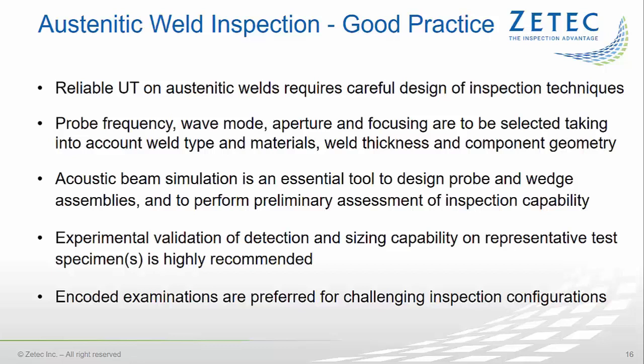First of all, reliable ultrasonic examination of austenitic welds requires careful design of inspection techniques and the use of state-of-the-art probes. The probe frequency, the wave mode, L waves or shear waves, the active aperture, and the beam focusing are to be selected, taking into account the base materials, the weld type and the weld material, and finally the thickness and the geometry of the component.